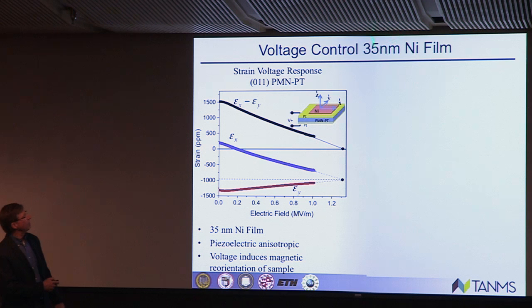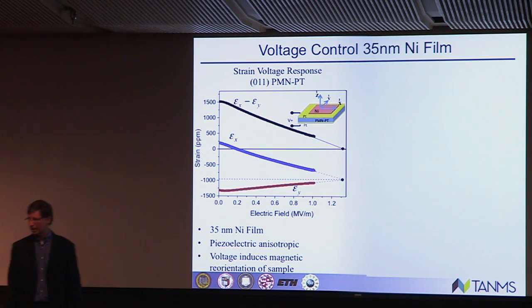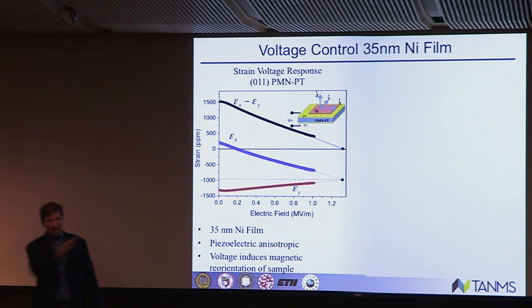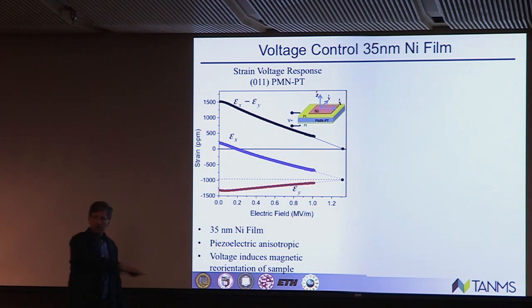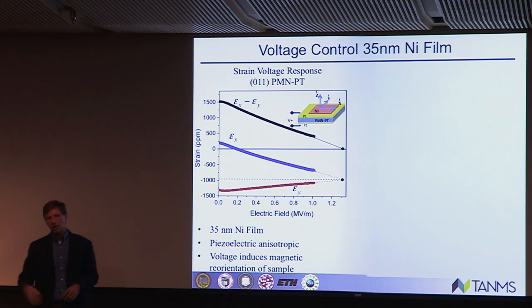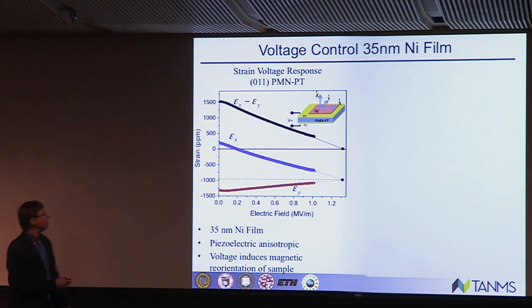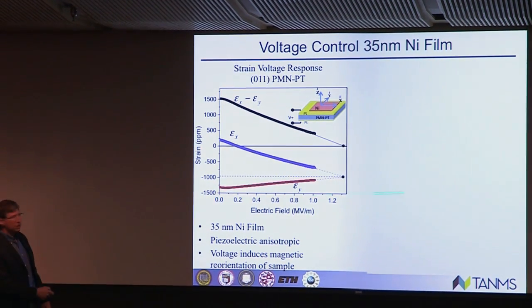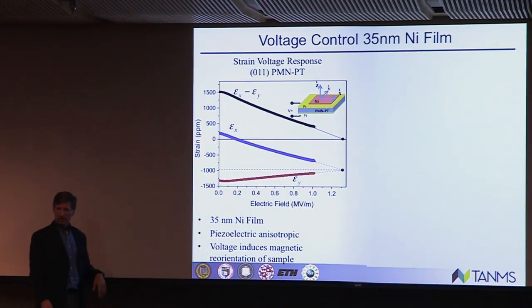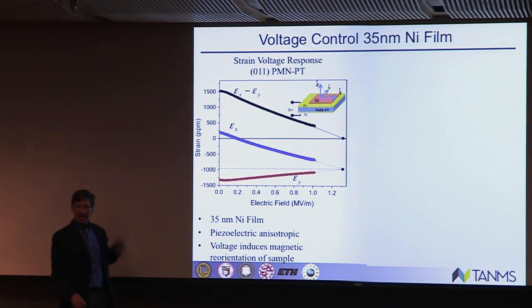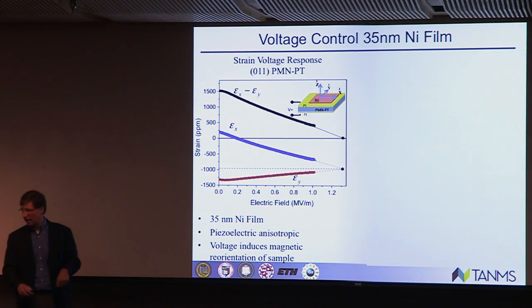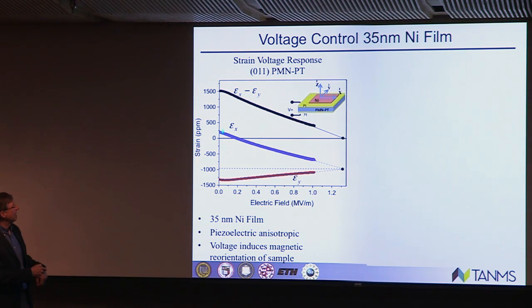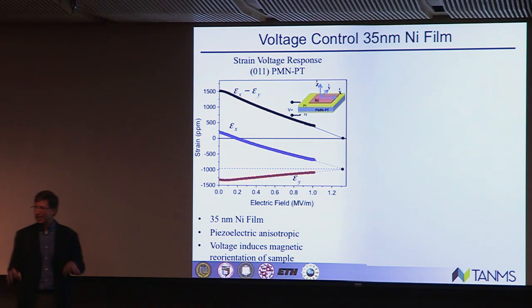We're going to start off, first film is going to be 35 nanometers thick. Now what's important about that thickness is all the magnetization states are now in plane. Did I discover that? No. That's well known in the community. So we chose a specific thickness of film. This is a plot of strain versus electric field for the ferroelectric that we're using, the PMN-PT. This cut here is anisotropic strain. So what you see here is the X strain and the Y strain. So X is this direction, Y is this direction. So they're different in plane.